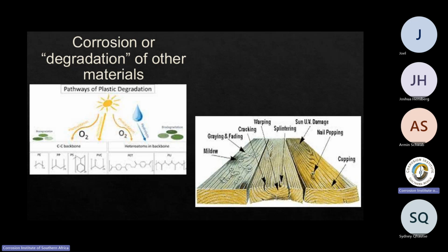But there are methods of preparing polyethylene to make items stick to it. Sometimes they induce a bit of flame, heat it, and once it's to a certain temperature, wipe it off with methyl ethyl ketone or tetrahydrofurane, which is some of the solvents that can get used. And now you get a proper bond between your coating system and the actual polyethylene. That's just some of the methods.